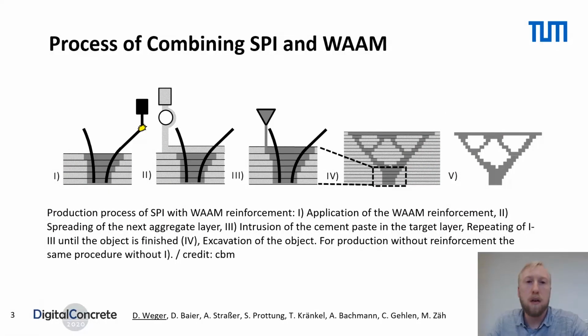Now let's have a look at how to combine these two processes. In the first step, a couple of centimeters of wire and arc additive manufactured reinforcement will be pre-produced. In the second step, a first layer of aggregate is spread, and due to the permeability, the grains fold around the wire and arc additive manufactured reinforcement. However, even after the application of the aggregates, there is still a space between the head of the reinforcement and the surface of the particle bed.